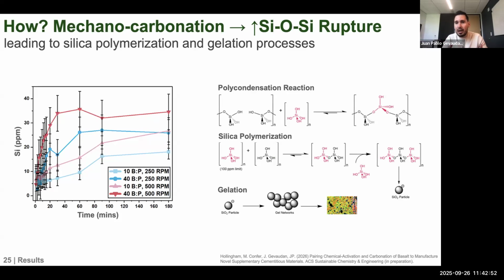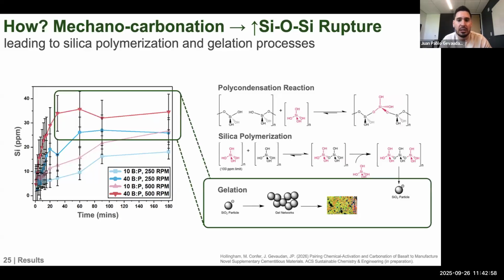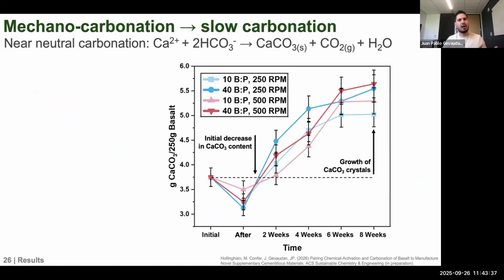Now, the silica polymerization happens quite rapidly and leads to gelation, which is the idea of these polymers going from oligomers into higher chain polymers and essentially creating a silicate gel that has a negative surface charge. Now, because we are also releasing magnesium and calcium, which I'm not showing here, that also allows gelation to speed up and form, as we have shown in previous work. So this is where we stand in terms of our understanding of this process, but I haven't talked about